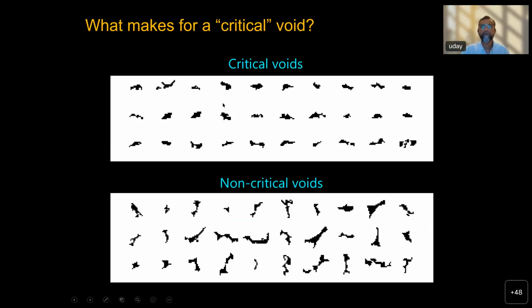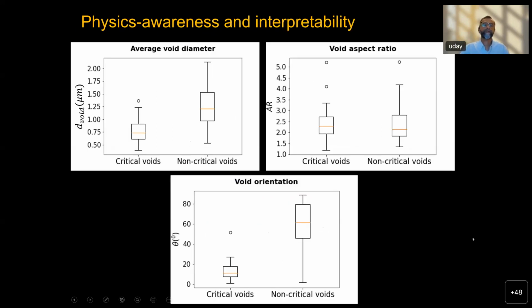These are critical voids and these are the non-critical voids. And as you can see, the critical voids don't look terribly different from the non-critical voids. But there are subtle differences, and the subtle differences are as follows. If you look at the average void diameter of critical voids, they tend to be smaller than the average diameter of the non-critical voids. If you look at the aspect ratio, the elongatedness, of the critical voids versus non-critical voids, they're not terribly different. But if you look at the orientation, it has a very strong effect. Critical voids are nearly horizontal with respect to the shock direction, whereas the non-critical voids are oriented much more parallel to the shock direction. So that orientation has a significant impact on sensitivity.